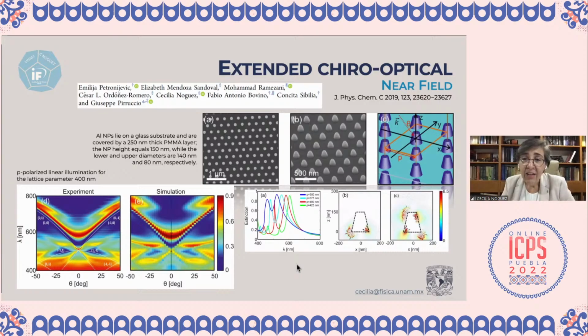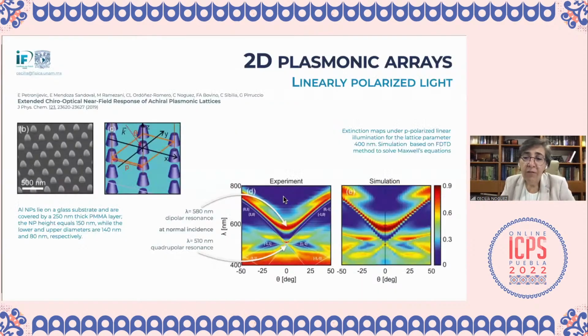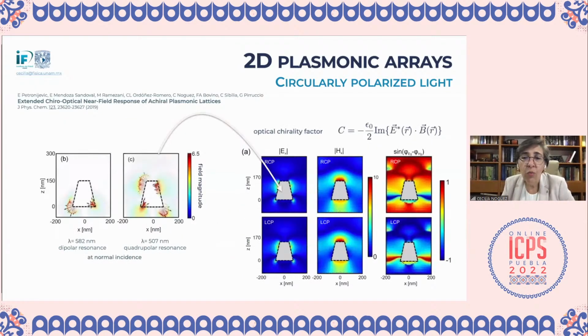And if you look at the near field, it's actually exciting. What we have found is that we can look at these resonances, the dipolar and the quadrupolar one here. With the quadrupolar one, we can increase what is called the optical chirality factor. That means we are breaking the symmetry of the near field in the system by using two-dimensional plasmonic arrays, and now we can increase the asymmetry of the near field in the system.